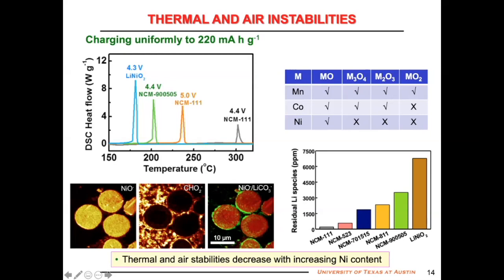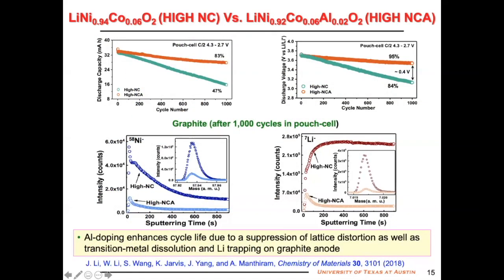So it is exponential, as you see here in this plot. So what do we do? Are we stuck or can we do something? Yes, of course we can do something. We are comparing here the same 9406 without any aluminum and here with 2% aluminum. You can see as soon as you put aluminum, you get much better cyclability, the red curves. You also get much better voltage stability.